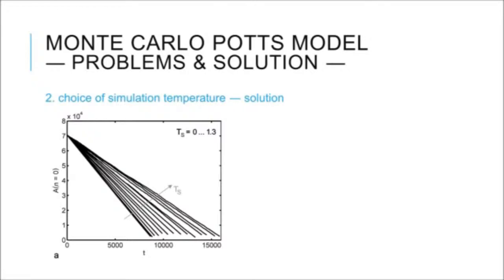This is a really good test. The area of any grain that you put into it, embedded in a larger grain, should always be a linear function of time. But you can see here that apparently the slope changes with simulation temperature — the larger the simulation temperature, the smaller the slope.